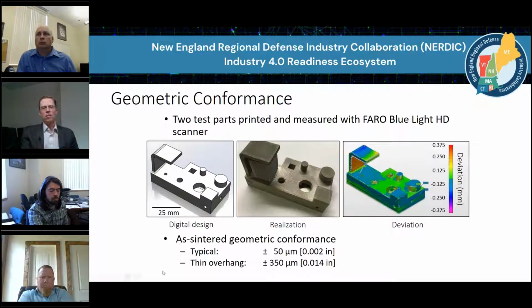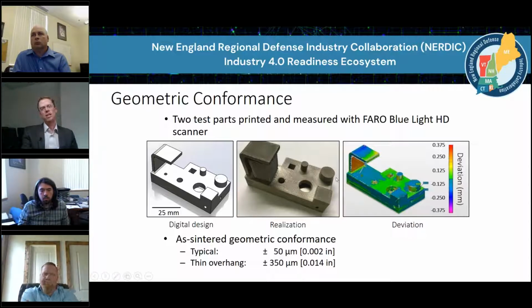This type of process is a near net shape process. To check how near net shape it happens to be, here is a digital design part. We printed off 2 of these parts to get a physical realization and scanned those parts. What we see over here compares the as-realized to the as-designed. In general, we get typical conformance of about 50 microns, or about 0.002 inch.